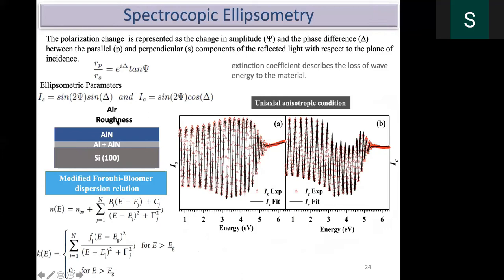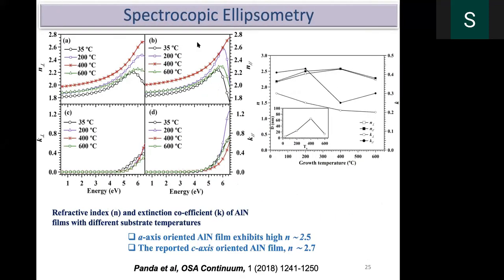With this model, if you plot, you will get two ellipsometric parameters, psi and delta. From this, we can calculate the refractive index of the material. That's what we did. And see different substrate temperatures. We have studied at parallel and perpendicular directions. This N is the refractive index. This is the counterpart,